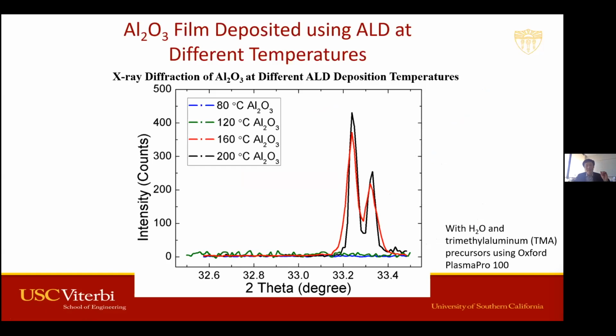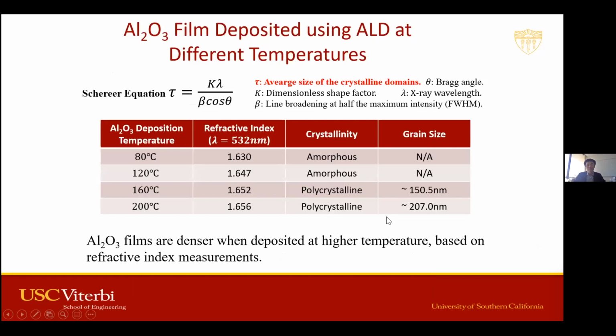One thing is that when we deposit this aluminum oxide layer using atomic layer deposition at different temperatures, the aluminum oxide layer will have a different crystallinity. Here it shows XRD data of the aluminum oxide layer deposited at different temperatures. You can see that the aluminum oxide layers deposited at 80 degrees C and 120 degrees C are amorphous, and those deposited at 160 degrees C and 200 degrees C are polycrystalline. And actually, here we summarize the properties.